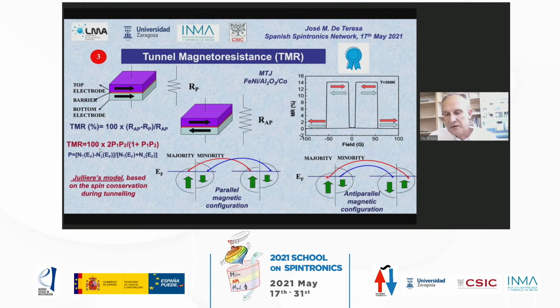In the antiparallel magnetic configuration, for the electron tunneling with a certain spin direction, now the majority density of states becomes the spin down subband. So now the electrons from the spin up subband have to tunnel to the available density of states in the spin down subband of the second electrode. And the second channel of conduction is electrons from the spin down subband to the spin up subband of the second electrode.